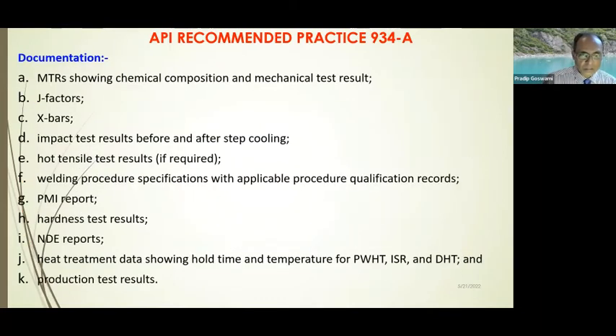And last of all, these are the typical documentation requirements one has to submit to the client. You can tell very well that everything is included. That means basically the material test report should indicate chemical composition, mechanical test results. You need the J factors, that is the temper embrittlement factor, for the test plates or for the base metals. You require the X bar or temper embrittlement values for the welding consumables. You need the impact test results before and after step cooling. You need the hot tensile test if it is mandated by the client. That is, typically it has to be done at the service temperature or the temperature which the end user or the client feels is required for this test.